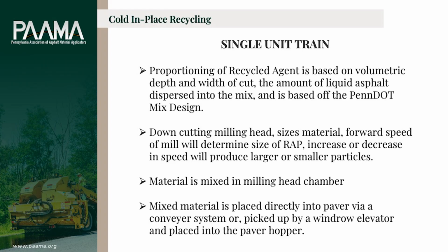So anyway, the proportioning of the recycled agent is based on the volumetric depth and width of cut. Remember I said there's 10 and 12-foot cuts that we can do. The amount of liquid dispersed into the mix is based off the PennDOT mix design. Every project has to have a PennDOT mix design. It's, as I said earlier, a down-cutting milling head. It sizes the material, and the forward speed of the machine is going to determine the particle size in that mix. Materials are mixed in the milling head chamber. We'll have a look at that in a minute. And mixed materials are placed directly into a paver via a conveyor system or picked up by a windrow elevator and placed directly into the paver.